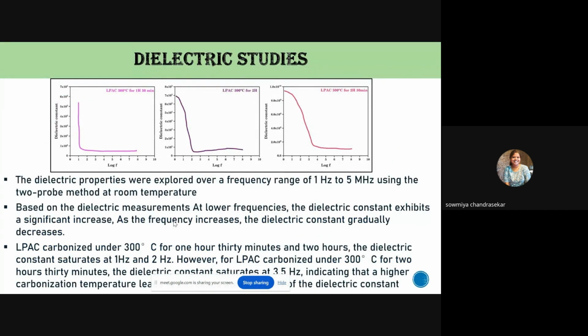Then the dielectric properties of the 3 samples have also been calculated. Based on the dielectric measurement, at lower frequencies the dielectric constant exhibits a significant increase. As the frequency increases, the dielectric constant gradually decreases. Lemon peel activated carbon carbonized at 300 degrees Celsius for 1 hour 30 minutes saturates at 1 Hertz, and for 2 hours saturates at 2 Hertz. For 2 hours 30 minutes, the lemon peel activated carbon saturates at 3.5 Hertz, indicating that higher carbonization leads to a higher dielectric constant.